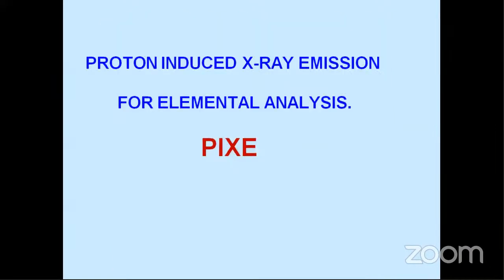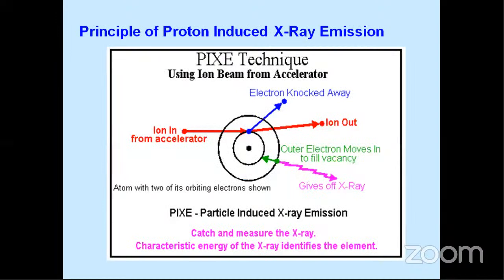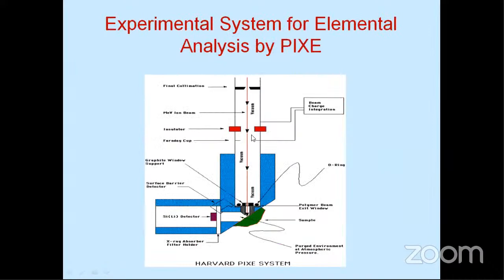So now there is another technique which is called proton-induced X-ray emission. The principle here is that when a high energy particle is bombarded, it removes an electron from the K shell, and X-rays are produced because an outer electron goes to the inner shell. So if you measure the X-rays, they give you an indication about the elements present in the sample. And therefore, this is the technique. So you have a sample here, you bombard it with protons, and the emitted X-rays you measure. And the X-ray spectrum will tell you which elements are present there. So this is the way.